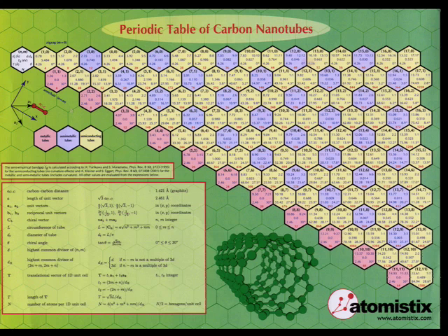How could you, for example, control the synthesis of nanotubes to get only these instead of these, where the size difference is basically 1 atom in circumference, which is really, really small? And we'll talk about that later. It's one of the emerging yet still unsolved problems in control of the synthesis of nanostructures like this. And you do have hundreds of chiralities in a diameter range of 1 to 3 nanometers.